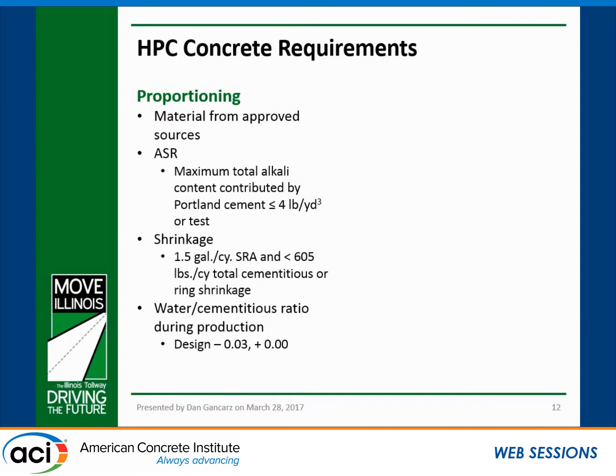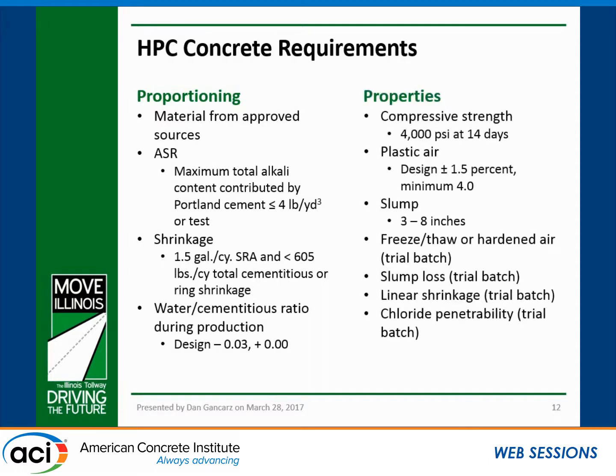For shrinkage mitigation, we have an option of doing 1.5 gallons of SRA per cubic yard and less than 605 pounds total cementitious, and that will waive the requirement for ring shrinkage. The producer's allowed to stray from that, but they have to perform the ring shrinkage test to prove that they are mitigating shrinkage concern. And then during production, we hold all of the Tollway mix designs to a water cement ratio tolerance. Basically, you can't exceed it, and you can go below it by only 0.03, because we want to minimize any potential effects from significantly dropping the water cement ratio.